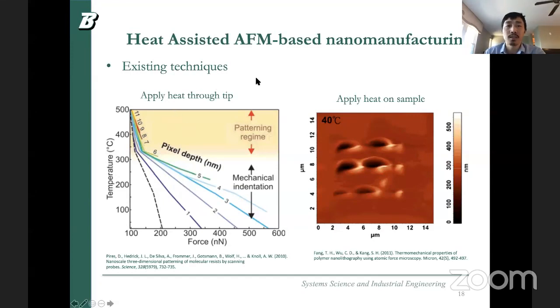There are some existing techniques using pure heat, where only heat is applied in AFM-based nanomachining. There are two techniques. First is applying heat through the AFM tip. The second is applying heat directly on the sample. When we apply heat through the tip, we need a very high temperature, even above 300 degrees C on the tip, so we can get some nanomachining patterning.